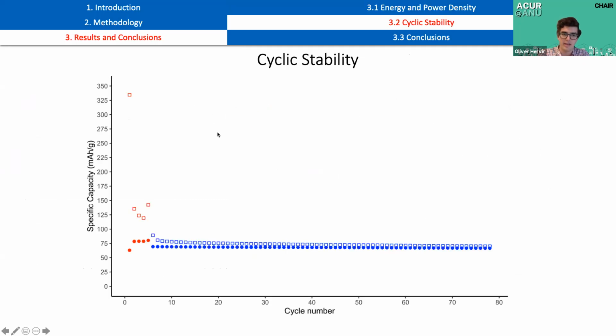Finally, I want to talk about cyclic stability. You can see here that initially the capacity drops quite quickly, but reaches a very stable plateau over 75 cycles. And this indicates a very promising result for the cyclic stability, although ideally we would have tested the battery for longer, but unfortunately that wasn't possible due to project time constraints.